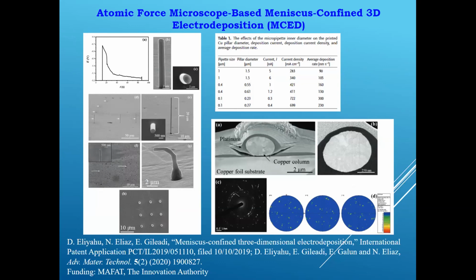The left figure shows the potential transient, side view in B and top view in C, of a freestanding straight copper pillar that was printed galvanostatically using an AFM feedback control and a 1 micrometer micropipette. The pillar is uniform, fully dense, with almost no porosity visible, and exceptionally smooth. You should compare it to the surface finish of the substrate, which is in this case a pure copper foil polished down to 40 nanometers colloidal silica.